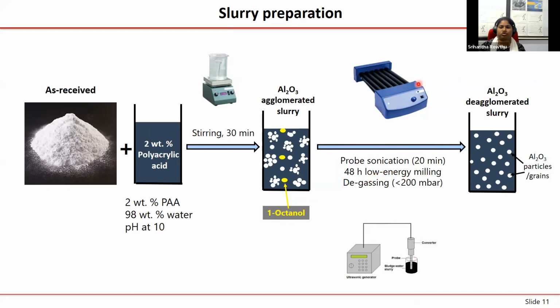Later on, we use low energy milling. You can put this slurry and roll it for almost 2 or 3 days. And finally, you can do degassing so that any air bubbles present will be removed from the slurry. So finally, you are able to achieve an almost de-agglomerated slurry. Here, each grain is a particle. Now, you can take this nicely de-agglomerated slurry and essentially cast it.